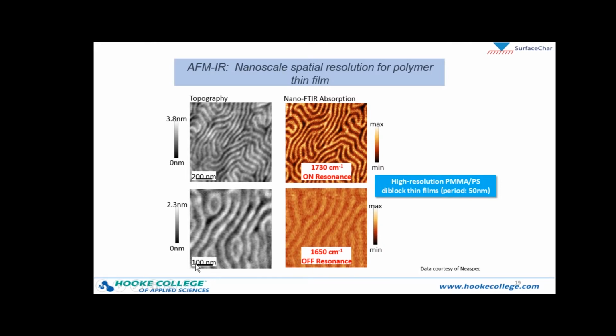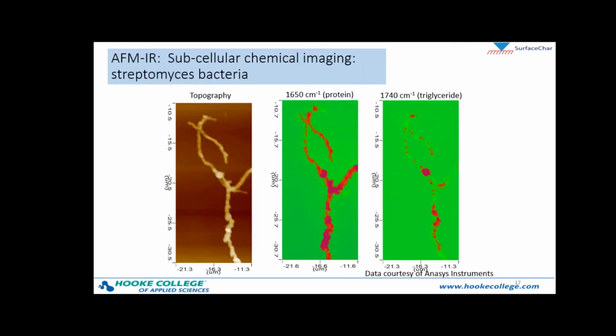And then here, even higher resolution. So here, this length here is only 200 nanometers. Here it's 100 nanometers. And you can see here they tuned off of the absorption peak and see very little contrast, showing that this contrast seen at 1730 wave numbers is real. So having this AFM platform to make these IR measurements and to build this IR information on top, at very high resolution, less than 100 nanometers, on top of the nanoscale topography and mechanical property information from the AFM, again results in a very powerful tool to provide a very complete characterization from many different angles of the sample.